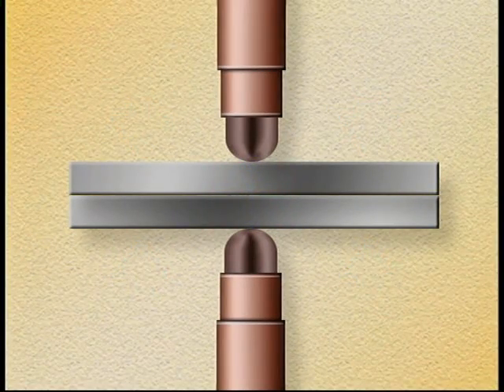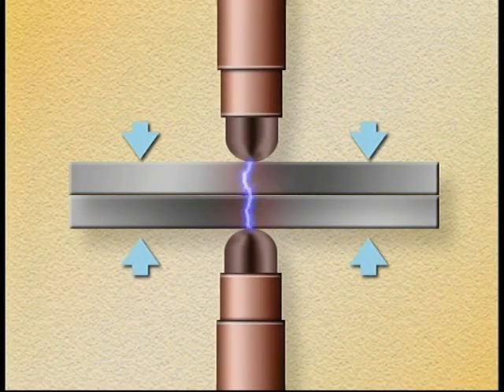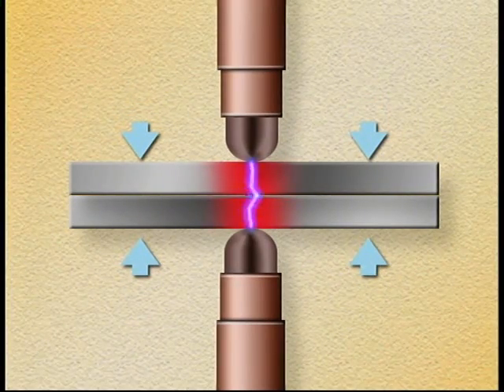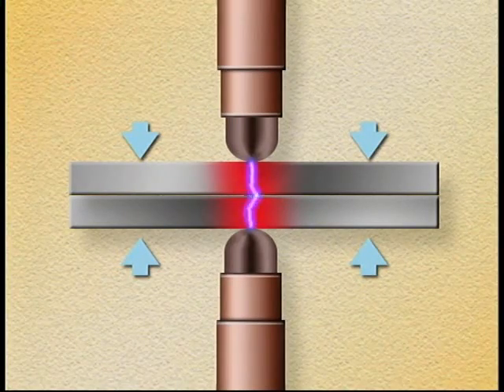In the opposite situation, reducing squeeze force increases the tiny separation between the parts to be welded. This increases resistance and results in more weld heat.